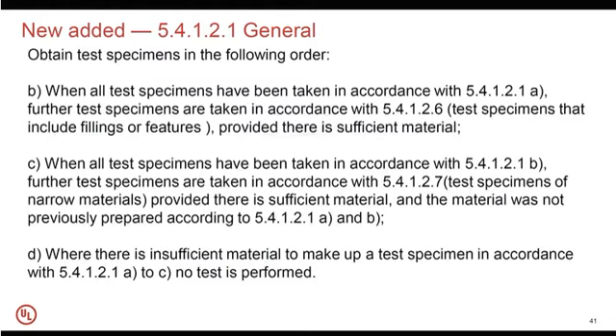So test specimens that include filling and features, provided that there is obviously sufficient material. And then there is the point C. So when all test specimens have been taken in accordance with 5.4.1.2.1b, further test specimens are taken in accordance with 5.4.1.2.7, which is test specimens of narrow materials, provided that there is sufficient material and the material was not previously